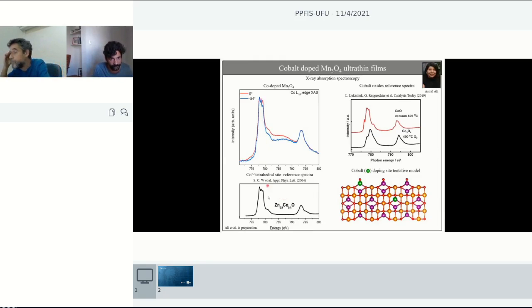You see here, from this three-peak structure, the cobalt sitting in a tetrahedral site. So from that, we can build this kind of model that we see here, similar to the other one that I showed you before, where we have the manganese 3+ in the octahedral site and the manganese 2+ in the tetrahedral site. We can judge with this combined experiment that the cobalt might actually be sitting in the tetrahedral site. And this is important because the chemical properties of this system will depend on that.